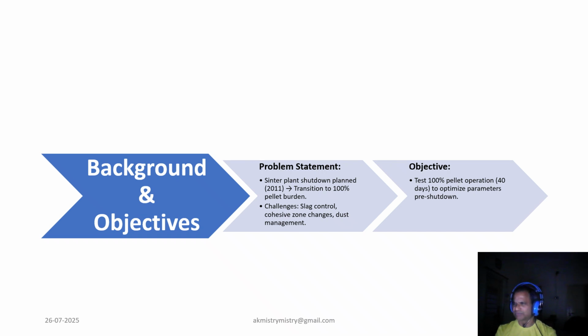Incidents start with some planned shutdown of the sinter plant, which leads to a drastic reduction in burden composition and leads to a situation of transitioning from a blend of pellet and sinter to 100% pellet burden in the blast furnace. These raise questions about slag control, which is supposed to be the most challenging, especially controlling the slag basicity, the cohesive zone, and the dust management. Our goal was to test 100% pellet operation for more than 1 month and fine tune parameters before making it permanent.